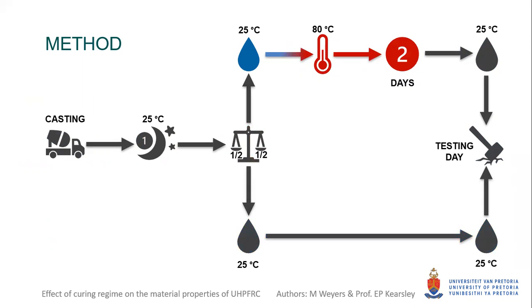To ensure that no thermal shocking took place, the water temperature for this bath was set to go up gradually from 25 degrees Celsius to 80 degrees Celsius. The specimens were left to cure for 48 hours. Thereafter, the temperature of the 80 degrees Celsius water bath was set back to 25 degrees Celsius. All the specimens were then left to cure at 25 degrees Celsius until the day of testing.